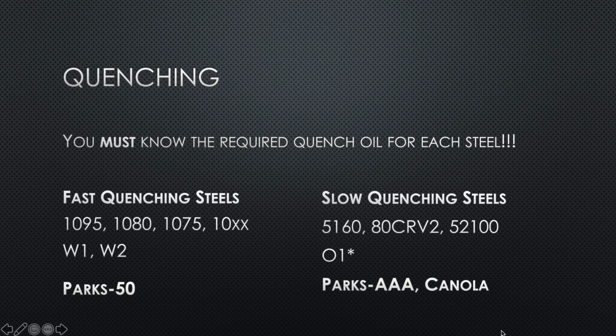If you quench something in oil that's not fast enough, you're not getting a hard enough blade. You're not getting what the steel can do. If you're quenching a steel in a quenching oil that's too fast, you're going to crack your blade, and even if you don't see it, you're going to have micro cracks in your blade. So make sure you understand this, and that's why I have 2 kinds of oil.